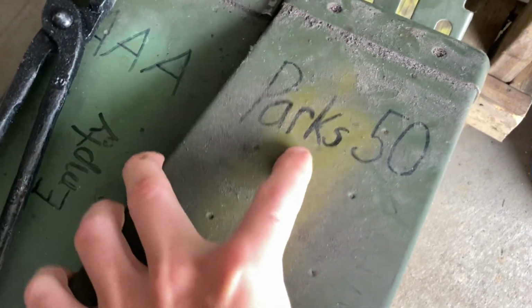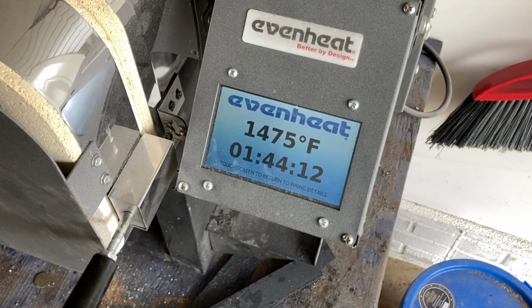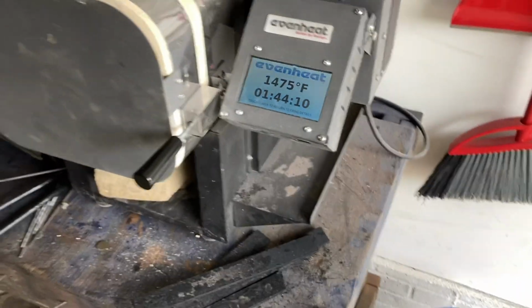Once it's time to quench, I get my Parks 50 quenching oil prepared and have it in this nice big ammo container in order to make sure that I have enough oil to heat treat properly. I have my quenching oil set up right below the entrance to my heat treating oven, and that enables me to get the knife into the oil as fast as possible.